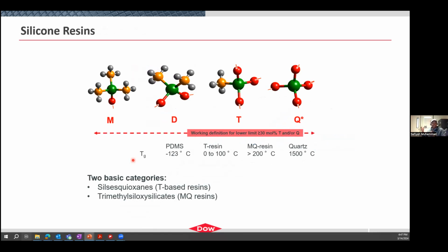Now, when you begin to incorporate T units and Q units, at least to 30%, then you begin to make silicone resins. And these are important because these are highly oxygen-rich species. And so they form these networked type structures. And we have two types of silicone resins. We have ones which are T-based. So they can be made up of any combination of these materials, but they have to have at least 30% T or Q added in.